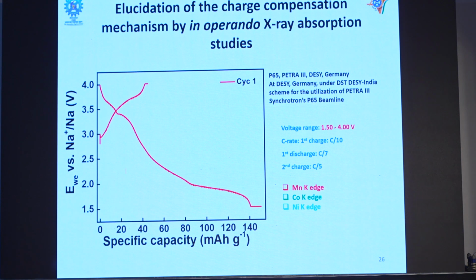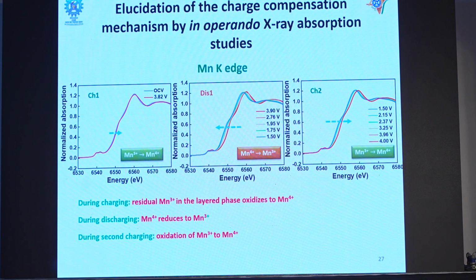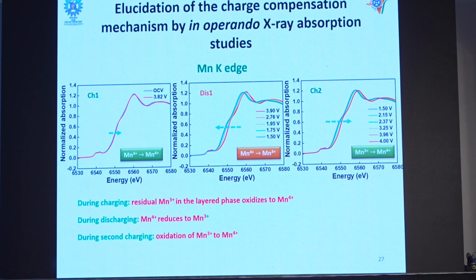Then we charge and discharge our cell, and we can see that the manganese edge during charging in the 4 volt region oxidizes to manganese 4 plus during the discharge, and some residual manganese is also oxidizing during the charge. And during the second charging, the process is continuing. Nothing more than we expected in the 4 volt region.